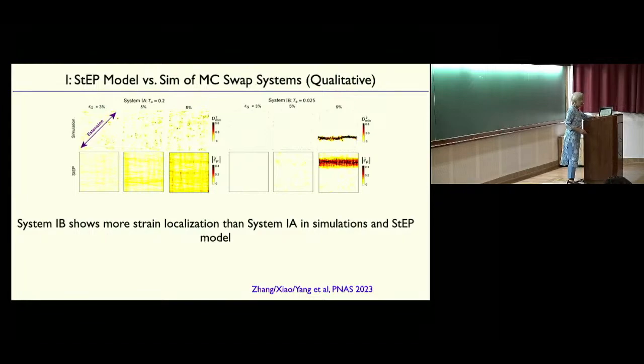Okay, so what you see here are pictures from the Monte Carlo swap systems. This is for the more ductile system. This is the map of plasticity in the simulation. Here's the map of plasticity in our model. What you see is that it remains delocalized, scattered all around. Whereas in this case, the more brittle case, you have strong strain localization in the simulation.